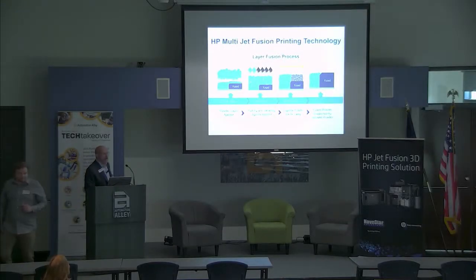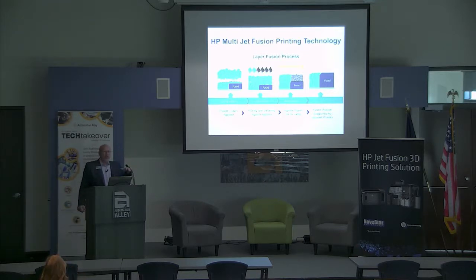Okay, so to dive in and recap a little bit of what was in the video, the fusing or the printing process is really a four-part process. We put down an 80 micron layer of fresh powder, and then we apply two different agents. The one agent that is indicated here with the black is what's called the fusing agent. And the agent that's indicated by the blue dots here is a detail agent.